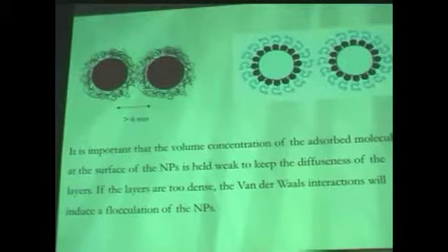It is important to see that the volume concentration of the adsorbed molecules at the surface of the nanoparticles is held weak to keep the diffusiveness of the layers. And if the layers of the molecule shell are too dense, we can obtain van der Waals interactions between those molecules, which will induce the flocculation of the nanoparticles, and this flocculation will induce their aggregation.